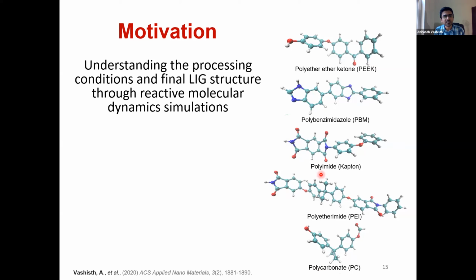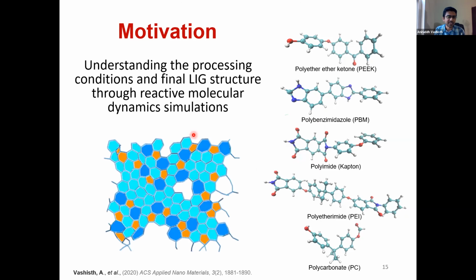All these 5 polymers have actually shown to make LIG when they are lased with a CO2 laser. So for example, here's a LIG structure that is made from Kapton. And as I mentioned earlier, it has a very interesting structure. You see there's a bunch of 6-member rings that are colored as light blue. There are 7-member rings that are colored as dark blue, and there are 5-member rings as well, which are colored as orange here. So it's a very interesting type of structure.